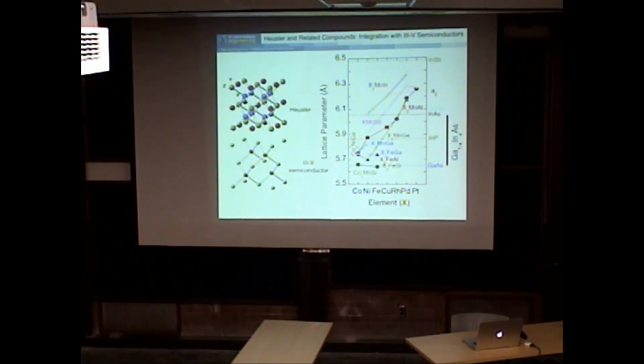Okay, so now what this has done for us is say, well, let's look at other compounds, these Heusler compounds. This iron 3 gallium is basically a Heusler compound. It's this guy here. And we can now look at others; there's a whole slew of them. I said there were thousands of them. And you can see here, if I just plot some of them up, these are the aluminides, this traditional metal manganese aluminum. You can see I'm spanning nearly all the lattice parameters of the 3-5 semiconductors. So we should be able to play games to actually get things to match. So typically, cobalt to manganese silicon, and excuse me, say iron 3 silicon, for example, or cobalt 2, or iron silicon, which I think should be here somewhere. Yep.